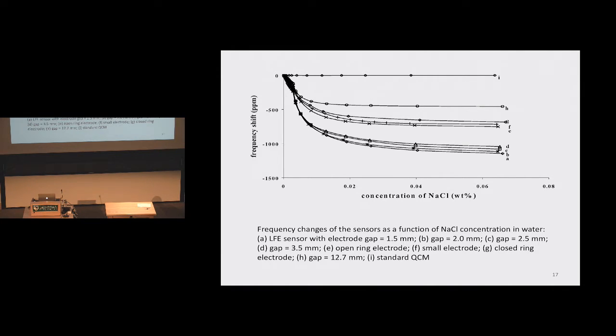H, E, F, and G all correspond to some of the modifications that we looked at, in particular open ring, small ring, closed ring, and so forth. And finally, this group down here was the lateral field excited device. A, B, C, and D correspond to different spacings in terms of the gap. You see here 1.5, 2, 2.5, 3.5, and the best one was 1.5 millimeters in terms of the actual gap. You have to be careful. If you make the gap too small, your sensing area is too small. If you make the gap too big, the strength of the signal goes down significantly.